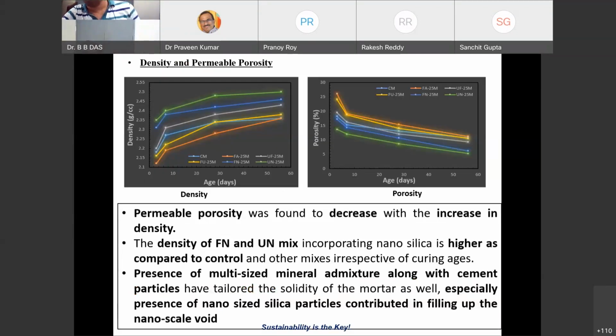Then your density and permeable porosity. Well, it is fine. You know the density is the green line. You can see here the ultrafine fly ash and nanoparticles, and in the particle packing concept also, we have got the best fit actually. So ideally, this will give you the highest density. You can see here the porosity is the lowest among all the mixes. So from the particle packing concept, when I did the statistical fit, I was very much sure the density and porosity were going to be the best.